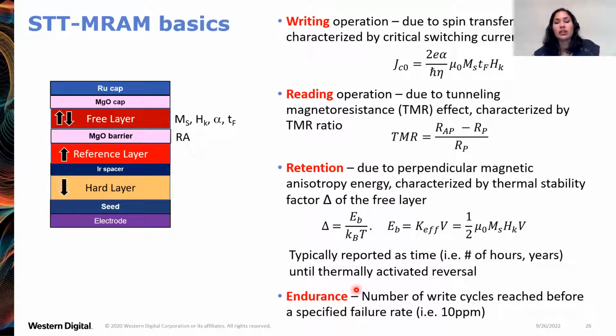And endurance, the number of write cycles reached before a specified failure rate. For example, a failure rate of 10 parts per million. So it's basically how many times can you pass a very high current through this very thin MgO tunnel barrier before you get a breakdown of the tunnel barrier causing a short. And that's the expected failure mode in STT-MRAM.